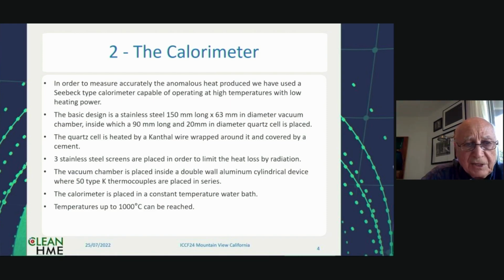The quartz cells are heated by a Kanthal wire wrapped around them and covered by a cement to isolate it. We also put 3 stainless steel screens in order to lower the heat loss by radiation, because we are in vacuum and the only heat loss we have is mainly radiation. The vacuum chamber is placed in a double wall aluminum cylinder where the 50 type K thermocouples are placed in series, and the whole calorimeter is placed in a constant temperature water bath. And we have reached more than 1000 degrees C.